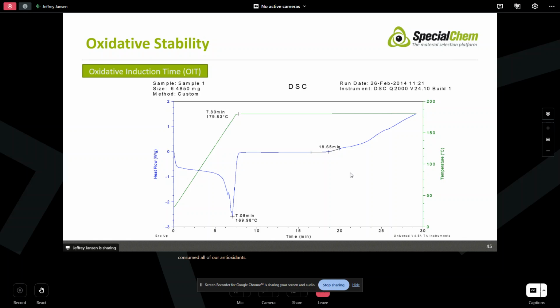So we can get a picture of the material if we understand what it was like right after molding, and what it was like after, say, 2 years in field service. How are we doing? Have we consumed all the antioxidants? Do we still have antioxidant left? We can get a good feel for the material. So again, it's a different experiment where we heat dynamically under nitrogen to get to an isothermal temperature. We hold that isothermal temperature for a couple of minutes, and then we turn on the oxidizing atmosphere.